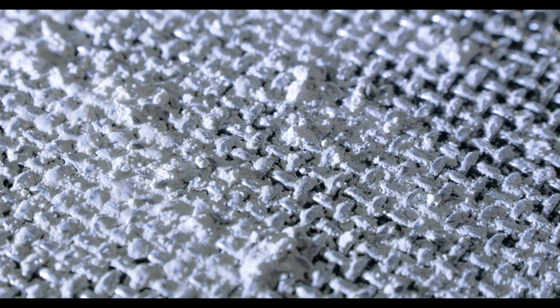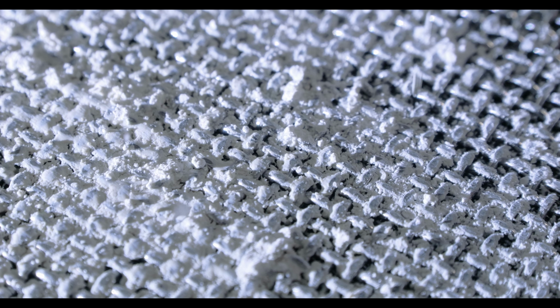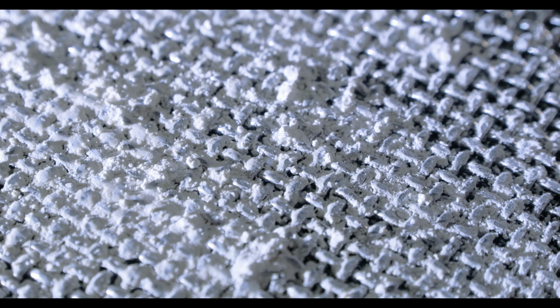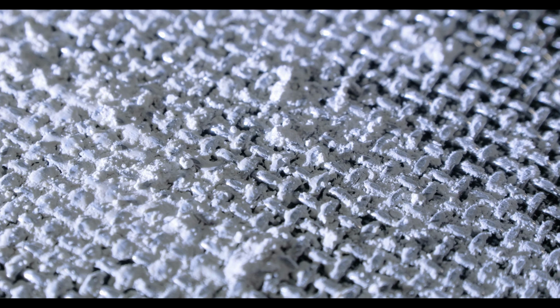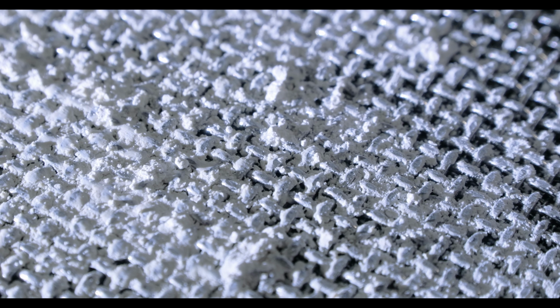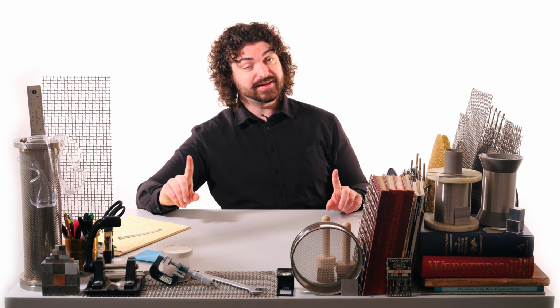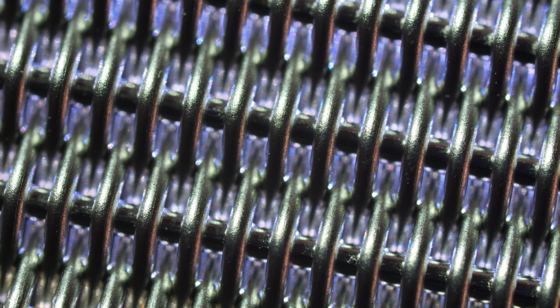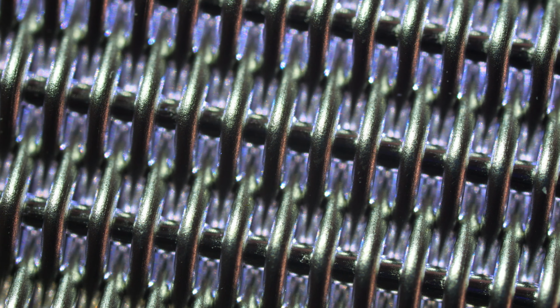Temperature fluctuations can interfere with cleaning mechanisms like pulse jet systems. If the particles become sintered or wetted due to condensation, standard cleaning cycles may fail to restore baseline pressure drop. This forces the system to trigger more frequent cleaning sequences, which may not be effective and can accelerate wear on the filter elements. In extreme conditions, cleaning systems may become overwhelmed, leading to persistent fouling and reduced system uptime. So, optimizing cleaning protocols for thermal conditions is essential to maintain long-term filtration efficiency.